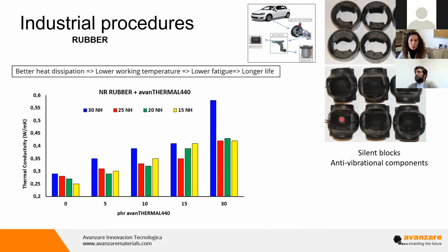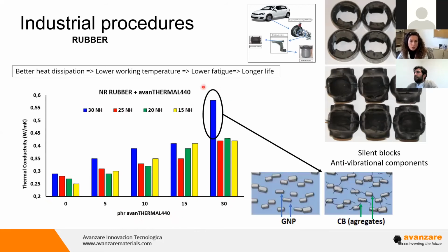These components usually work at higher frequencies, so they work under important fatigue and accumulate a lot of heat. So if we reduce the working temperature of these materials, we are reducing the fatigue and increasing the life. It's important to highlight the results that we can observe here. This is the industrial formulation with different quantities of carbon black and different quantities in phr of our Avanthermal 440 conductive additive. In this case, it's important to highlight that what is happening when we increase the thermal conductivity a lot is that we are creating a very cohesive network with graphene nanoplatelets and the aggregates of the carbon black. So it's really efficient to move the heat from one part to another.